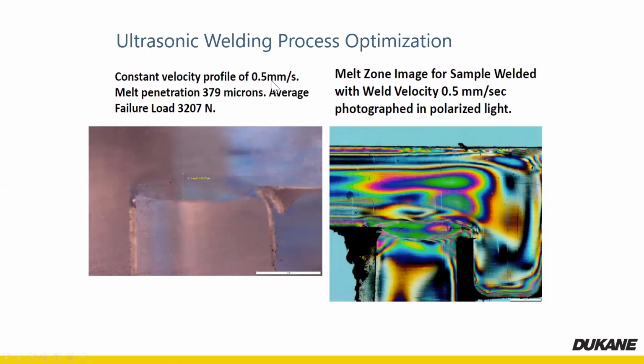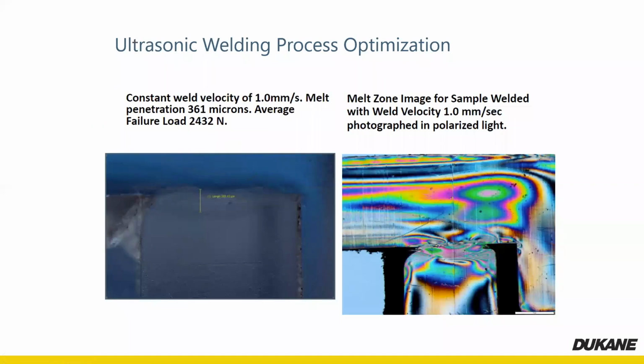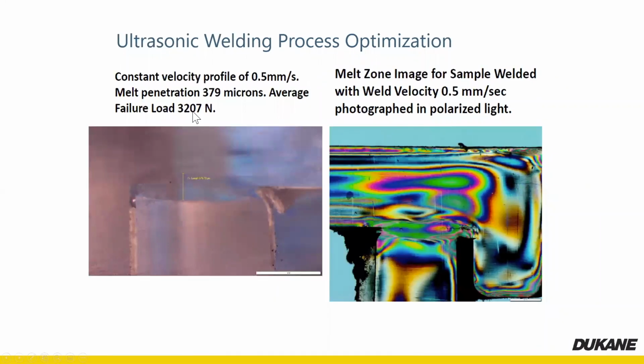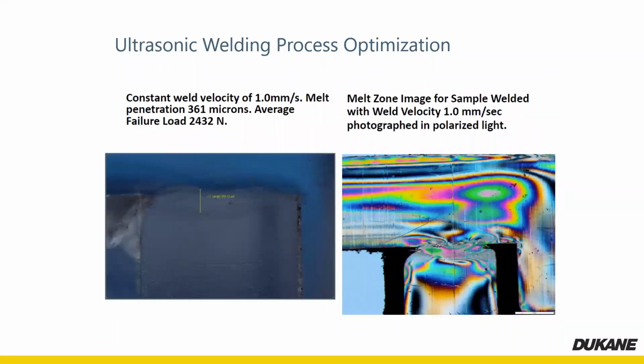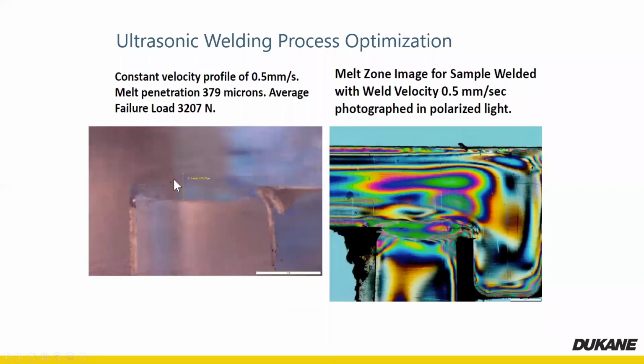This is half the speed. So we went 0.5 millimeters per second instead of the 1 millimeter per second. You can see that the weld penetration got further into this joint. We had a failure load from, and I'll go back again, so we went from 2,400 Newtons to 3,200 Newtons. Again, from 1 millimeter per second to 0.5 millimeter per second. And you can see the increased area.